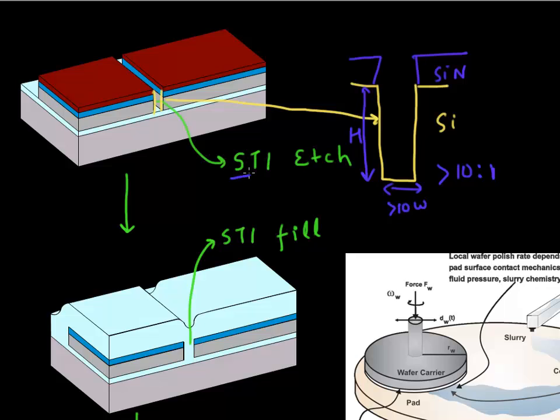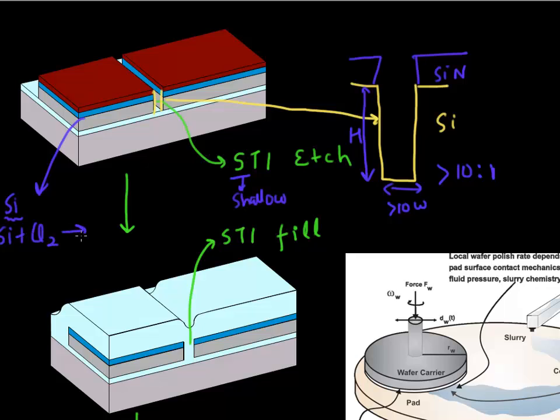So this 'shallow' in shallow trench isolation is really a misnomer, because it's quite deep if you look at the aspect ratio. The other thing is the chemistry. We use a dry or plasma-based chemistry for this STI. The typical chemistry used for silicon etch is a chlorine-based chemistry. Silicon reacts with the chlorine ions and forms SiClX, which is essentially a volatile compound that goes away from the trench — and that's why you're able to continue to etch and make this feature.